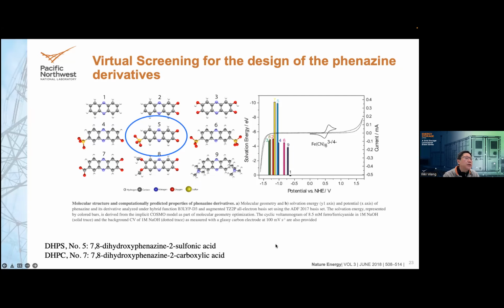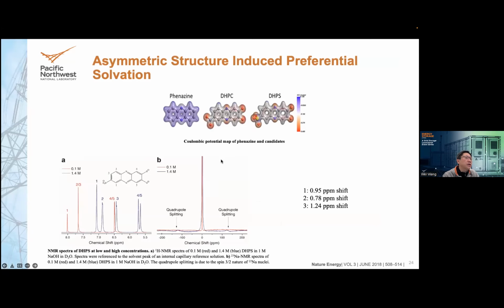If you are working on the redox flow battery on the organic materials, most of the studies are going through this type of route. So in the organic space, most of the time we capitalize on the preferential solvation to increase the solubility of the organic materials. What that means is, in this case the phenazine, the electron distribution on the pristine material molecule is symmetric. So this is why it does not dissolve in the water that much. And to achieve the solubility, you have to create some kind of asymmetry in the structure, so that the asymmetric distribution of the electron density will intensify the solvation with the water, with the surrounding microenvironment in the electrolyte.